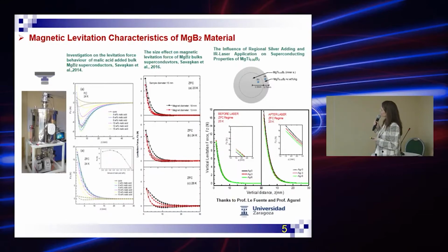And in the other study, we investigated the size effect on magnetic levitation force, and we observed the magnetic levitation strongly depends on the diameters of the bulk and permanent magnets. And also we investigated the surface laser treatment on levitation force properties of silver addition to titanium doped MgB2, and we determined that after laser treatment magnetic levitation force values were enhanced 2 times.